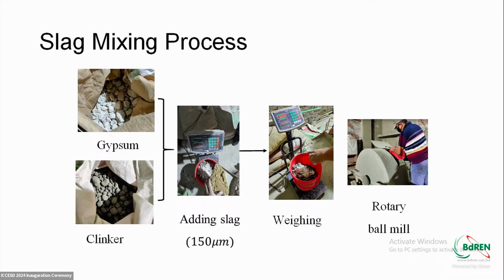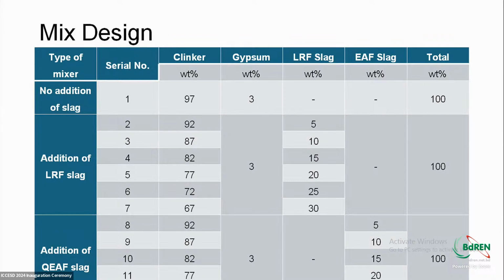In a small rotary ball mill, we mixed gypsum, clinker, and slag, so the final product was cement. The mix design was like this: clinker percentage was replaced by 5% to 30% LRF slag. In sample number one, there was no replacement, only gypsum. In samples 2 to 7, there was replacement by LRF slag from 5% to 30%, and in samples 8 to 11, clinker was replaced by EAF slag from 5% to 20%.